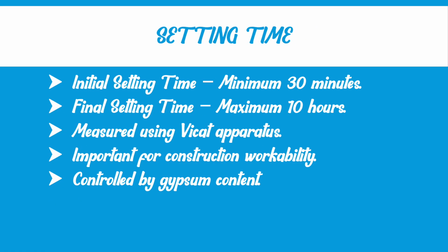Then setting time. Initial setting time is minimum 30 minutes, and final setting time is maximum 10 hours, measured using the Vicat apparatus. It is important for construction workability. It is controlled by gypsum content.